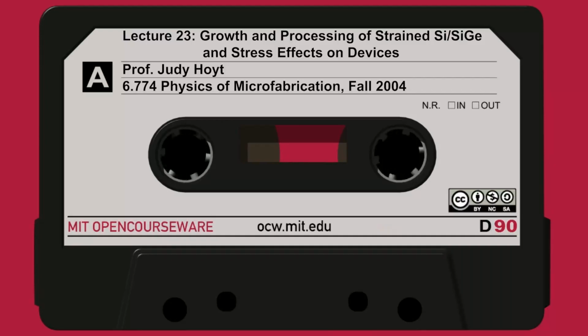So these layers are used to take the silicon channel and either stretch or compress it mechanically. By stretching and compressing the lattice in the channel, you can enhance the mobility, as it turns out. Enhancing the mobility means you get a higher current drive for a given voltage, so the devices will switch faster. So for enhancing CMOS, some of these materials are now in production. Intel has a new Pentium in production using this type of technique.